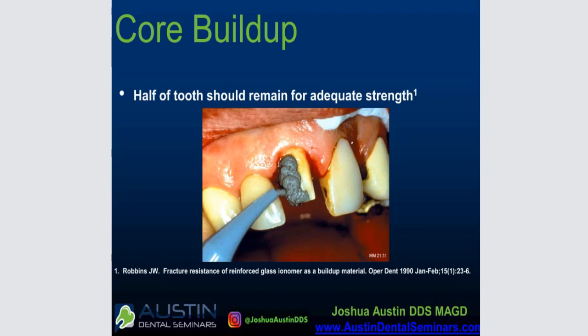Not an ideal situation. You're looking at Miracle Mix being used here as a core buildup in the anterior to go under a PFM, which is certainly an older school of dentistry for sure, but about half that tooth remains. We don't have any pulpal issues here, and so this would work very well to just round out and give us good prep form. And glass ionomers work great for those types of situations. Either of the two glass ionomers I'm going to show you at the end today will work great in this situation as well.